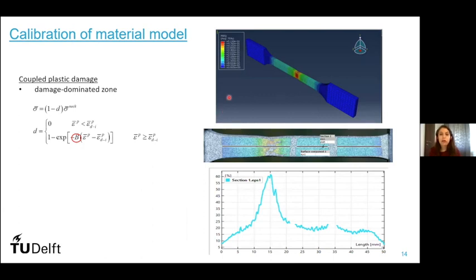Also, I made a comparison between the model and the digital image correlation. So in terms of plastic equivalent strain, the results are quite similar. For example, for this particular specimen in Abaqus, I had 61% plastic equivalent strain, and in DIC, I had 60% plastic equivalent strain. So this demonstrates that the calibration was done correctly.